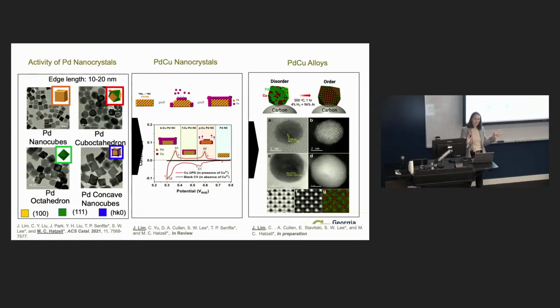Then he looked at, okay, well, once I can look at the activity of these crystals, can I then add palladium and copper, I should say, and looked at how you could manufacture this copper through just coating with copper. And then the third thing we wanted to look at was if maybe coatings are not the most active or most ideal because there's going to be different surfaces that we want. And so we're looking at if we could create ordered and disordered alloys. Again, one problem with coating metals is that they can migrate through the catalysis, and so this can be a non-stable form of a catalyst, whereas when you move to alloys, the thermodynamics seem to settle out and you can get potentially more stable performance.